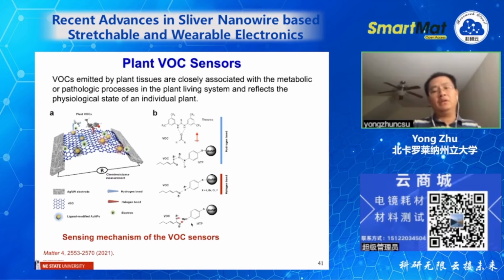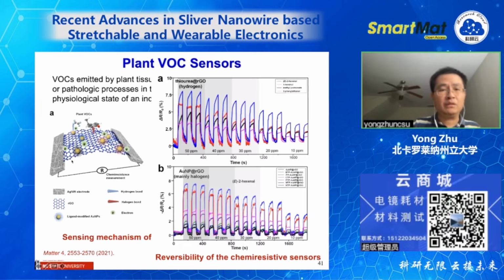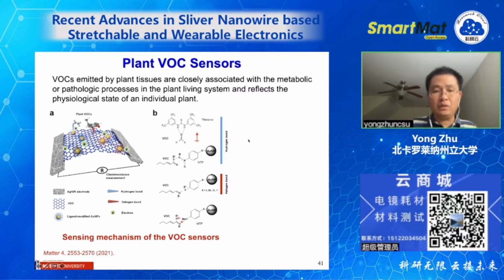And then also we're talking about plant sensors. In this case, particularly, it's the VOC sensor, because VOCs emitted by the plant can be associated with the physiological state of individual plants. In this case, our nanowires are basically used as electrodes, and the functional device is graphene with ligand-modified nanoparticles. They are pretty much reversible because we use hydrogen bonding and or halogen bonding, because these are reversible.